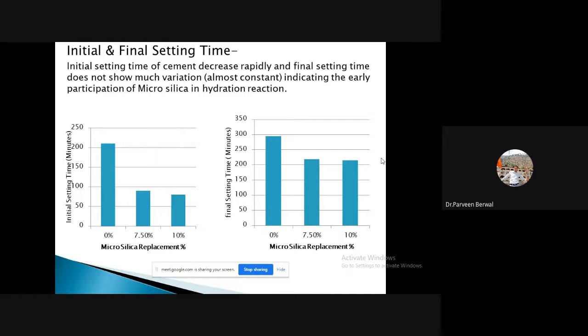This is for the initial and the final setting time. Initial setting time decreases as we increase the microsilica content, but in the case of final setting time, it does not gradually increase or decrease, as you see. The initial setting time change is large, but in the final setting time the decrement is not as high as you see in the initial setting time.